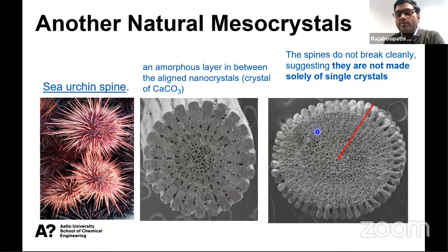If it is a completely pure single crystal, when you break the crystal, the cleavage plane is very clean. But here, the cleavage plane is not clean. It is not very smooth. So we can say that this spike is not only made up of pure crystal material. There is some other entity between the crystals. Here, it is amorphous calcium carbonate.